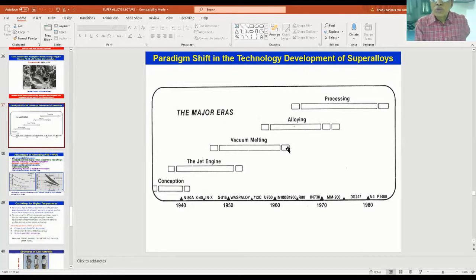Subsequently, in order to perform very well in service, superalloys should be very clean. They should not have any inclusions. They should not have any primary carbides undissolved. Therefore, from air induction melting, it has been shifted to vacuum melting. Now, superalloys are produced by vacuum induction melting process. Already I have discussed with you the variations that have come, and the processing now involves vacuum induction followed by vacuum arc remelting or electroslag refining.